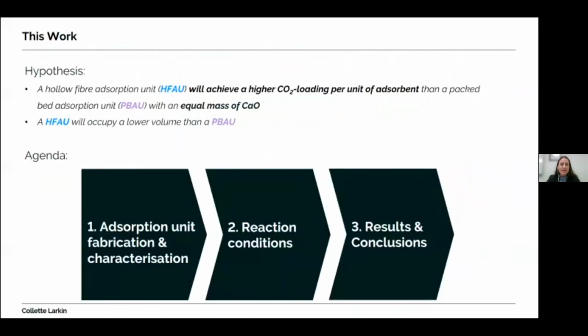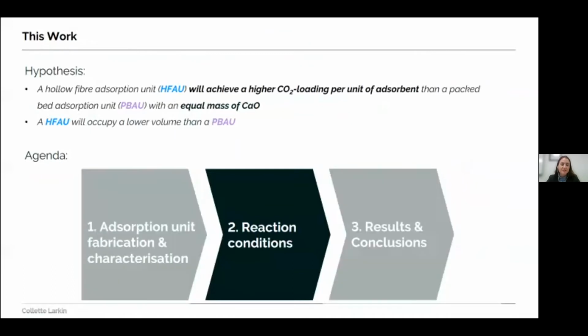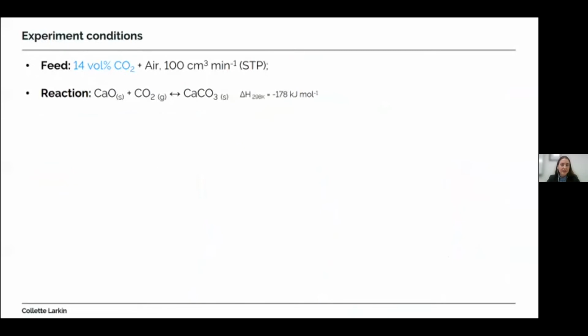So moving on to the experiment conditions, which are used to test the performance of the adsorption units in terms of their CO2 capture. So the CO2 capture performance of the hollow fibre adsorption units was tested using a feed of 14 volume % CO2 balanced in air at a flow rate of 100 millilitres per minute at standard temperature and pressure. A concentration of 14 volume percent CO2 was selected as it mimics the concentration of CO2 present in a vehicle exhaust. The reversible reaction that takes place between the solid calcium oxide and gaseous CO2 produces solid calcium carbonate.